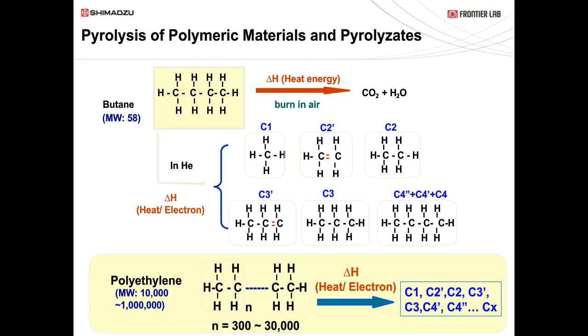As I mentioned, pyrolysis is typically done in helium. If you look at butane, which is C4H10, and apply heat in the presence of air—combustion—you are actually breaking down this molecule into CO2 and H2O. Whereas when you apply heat in the presence of helium, an inert gas, you are actually breaking this molecule into smaller fragmentation that you can then identify to the polymer. In the case of polyethylene, when you apply sufficient heat in the presence of helium, polyethylene starts to break down into fragmentation. It's very important to know the sufficient amount of heat; otherwise, if you don't know how light or heavy your polymer is, you might overheat or underheat it, making it very hard to identify the fragmentations.